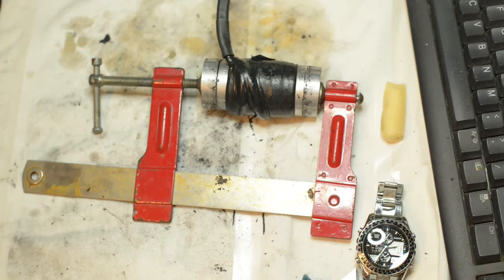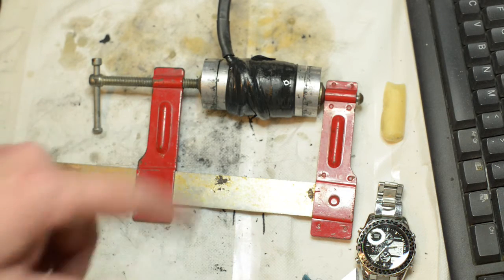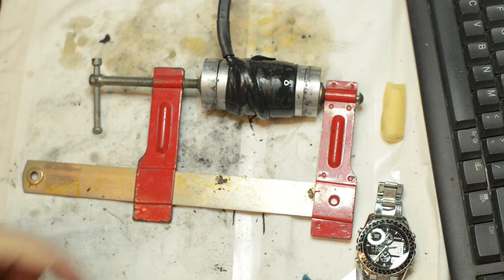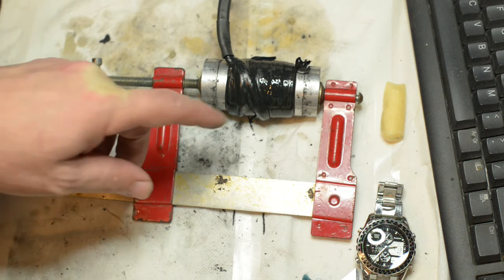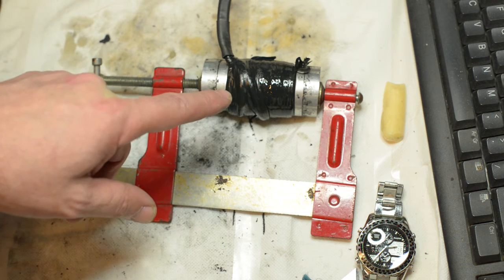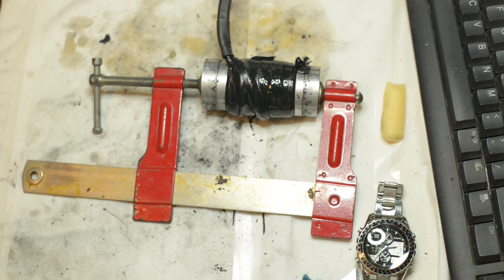During the first 1.5 to 3 minutes of the curing process, 10 volts at 15 amps will be applied to the coil. The external temperature of the mold should rise to about 80 to 85 degrees centigrade. During this time, the viscosity of the mixture is rapidly changing, and it will eventually seep through the gaps between the main mold body and mold end caps. However, due to a combination of temperature change and internal pressure buildup, alongside the fact that the viscosity is still changing and thus the mixture becomes even thicker, that same mixture will eventually cease to be able to escape through the gaps any further. Therefore, a form of internal balance has been reached, and curing progresses from that point onwards.